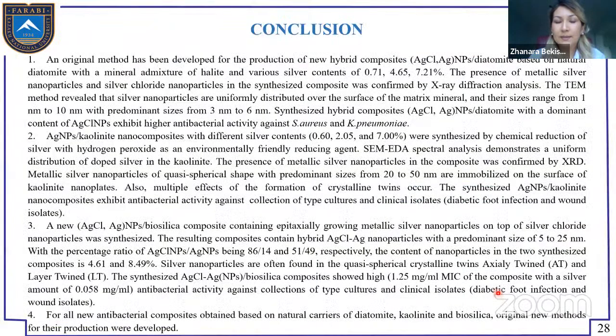And next, this is the conclusion. The original method of synthesis of hybrid composite based on diatomite was developed with different concentrations 0.71, 4.65, and 7.21. And the presence of metallic silver and silver chloride nanoparticles was confirmed with X-ray diffraction, and the size distribution was studied by transmission electron microscopy, with size from 3 to 6 nanometers, and the synthesized hybrid composite showed antibacterial